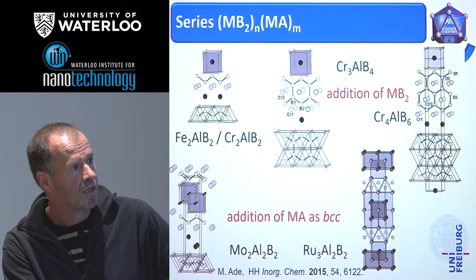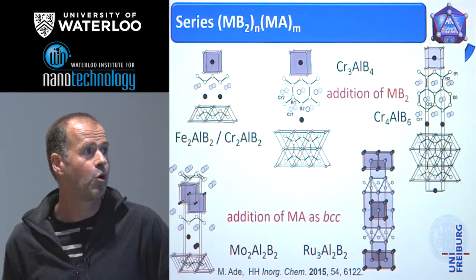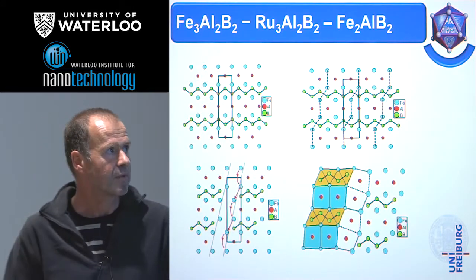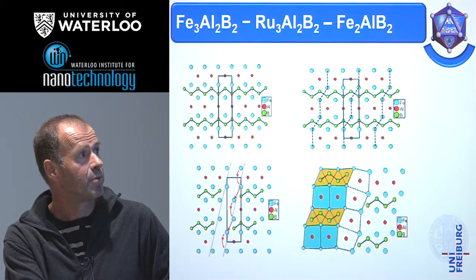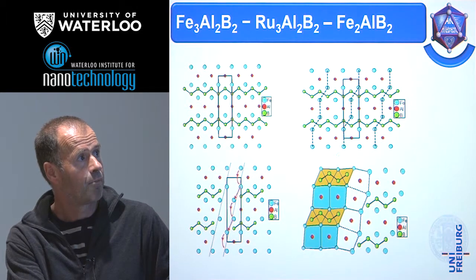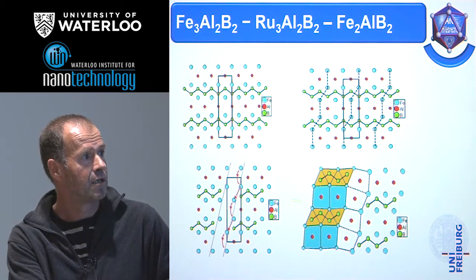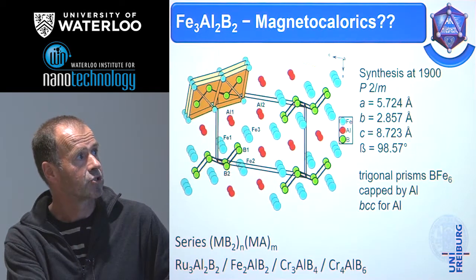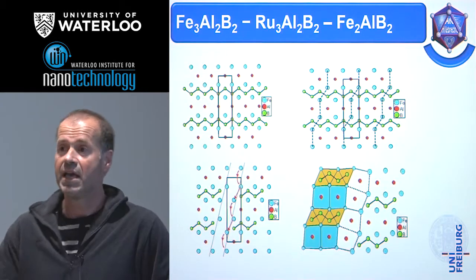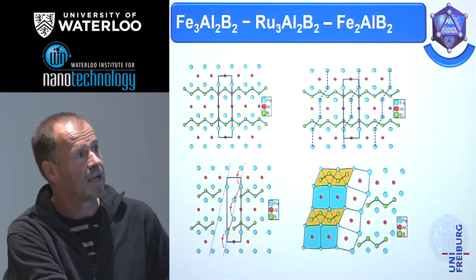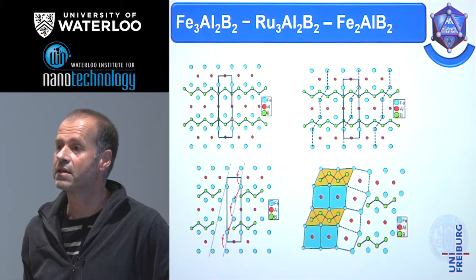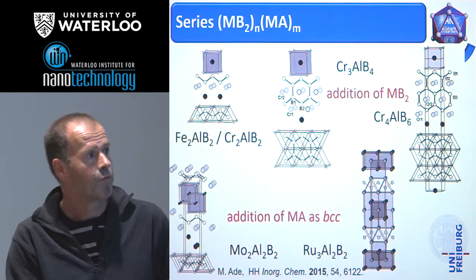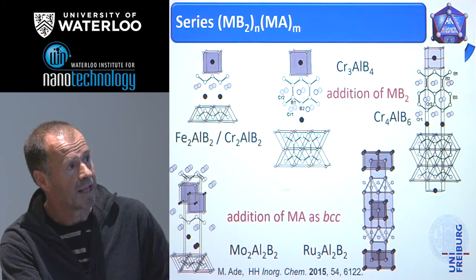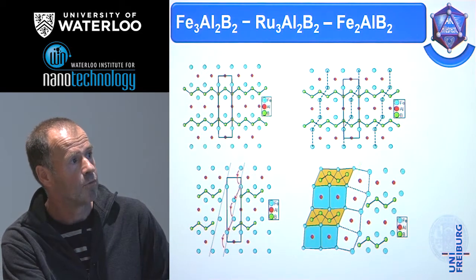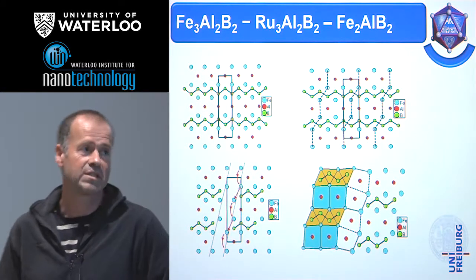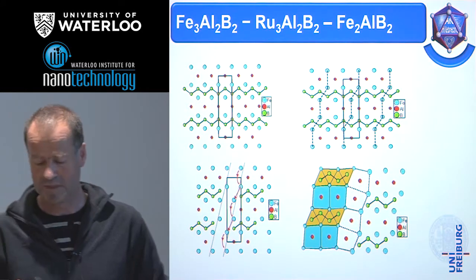And you see that this composition is very similar to what we had here, and we could show that the relation is quite simple. Starting from the simple compound with the zigzag chain, we cut out a part of the structure, do a shift, and bring it together again and get exactly the structure we had here. That means we just add an additional layer of an intermetallic part with the BCC characteristics. And so in contrast to this example where we had the layer parallel to the boride structure, here it is more or less perpendicular to the boron zigzag chains. And it was an idea we did not regard when we developed our building principles.